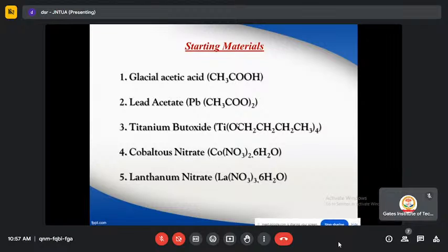After this continued for half an hour, titanium butoxide was added drop by drop, and the entire solution was allowed to mix carefully for 2 hours, and a solution of ethanol and water was added. After some time, a gel-like solution was attained. This gel was dried naturally for nearly 2 days, that is 48 hours. After that, it was heated in a hot air oven for about 1 hour. Through this process, a rigid crystal form was acquired, which was ground into a fine powder.